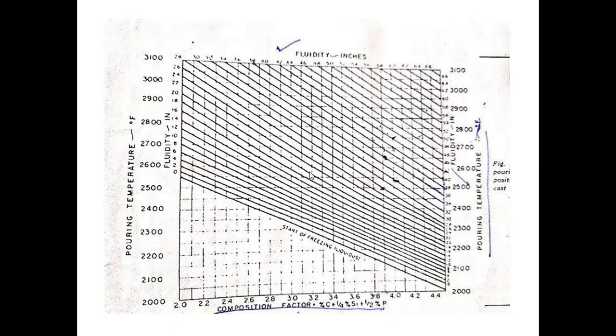If you are pouring a thick casting of 150 kg, then pouring time doesn't matter. But take a 150 kg tractor transmission case. In that case, the general wall thickness will be 7 mm and the height of the casting will be around 300-350 mm in the cope box. At that time, pouring time and pouring head are most important, and a thumb rule cannot work there. That's why AFS have done the research and published the book.